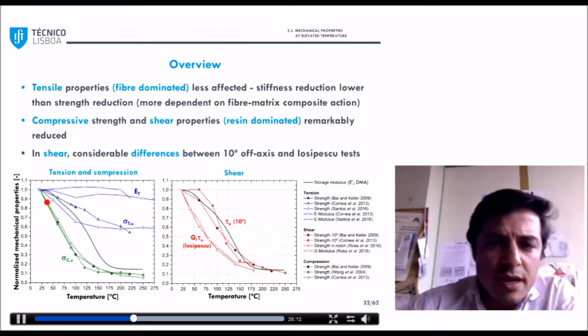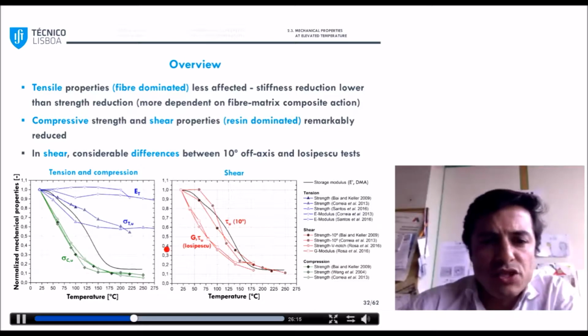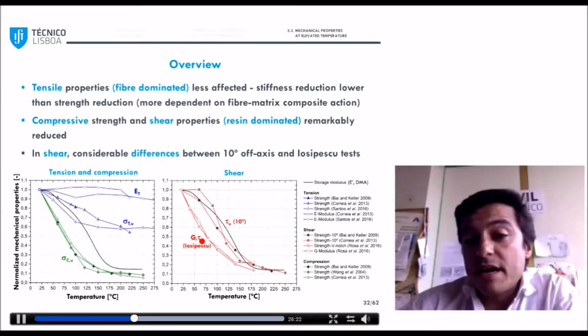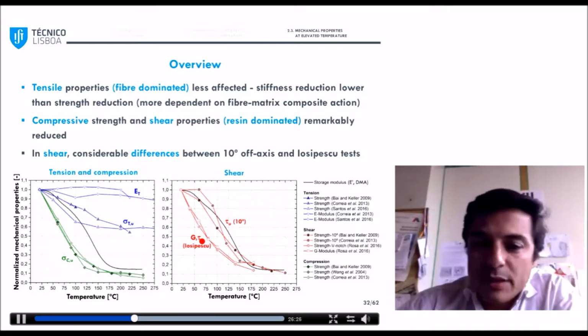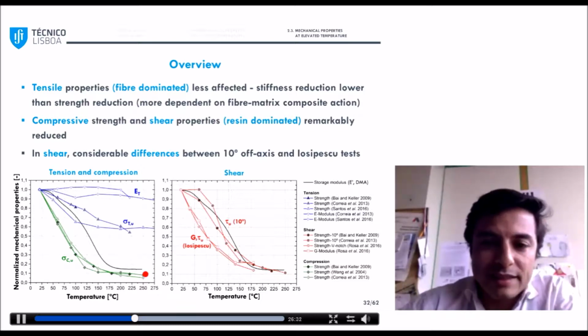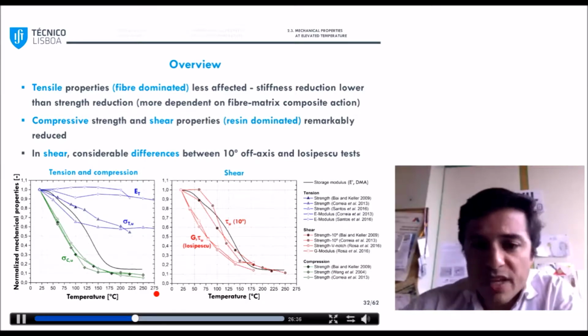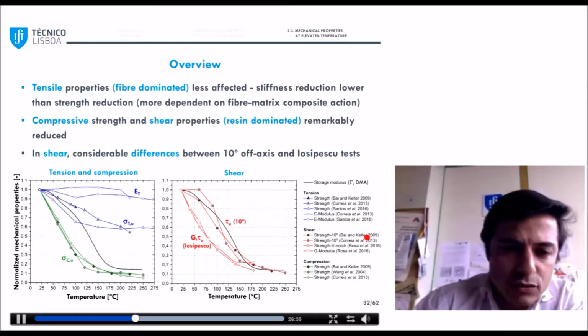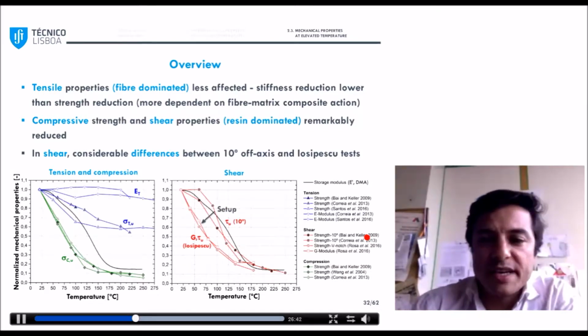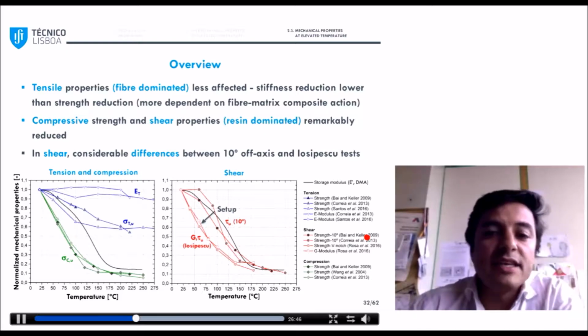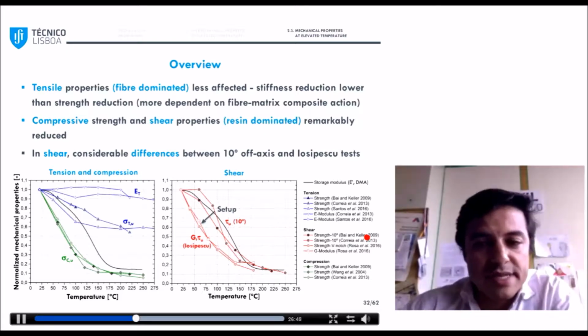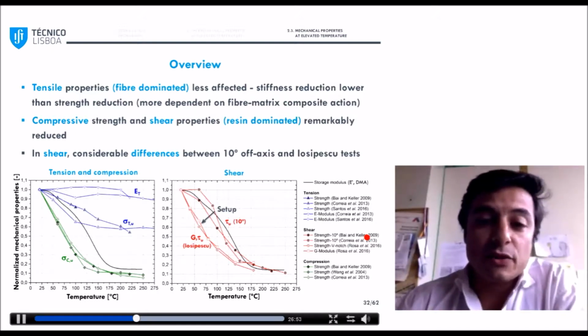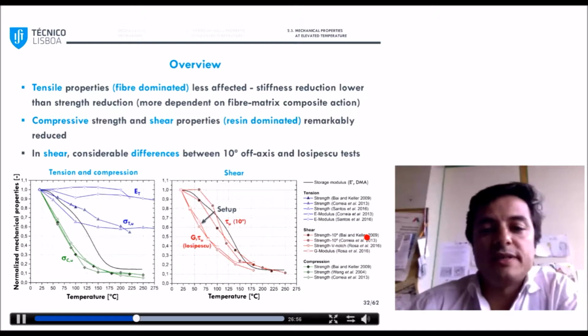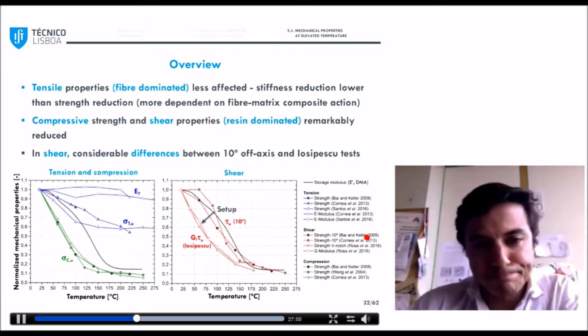Now, compressive strength, which you see in green, and the shear properties that you see here in red, both the shear strength and the shear modulus, are all resin dominated, and you can see that consequently they experience much higher reductions with temperature, becoming almost negligible at the end of the glass transition process. For the shear strength, I would also like to mention the significant differences we obtained from 10 degrees off-axis tests and the Iosipescu setup. So here you see that the setup we use has a big influence because for 10 degrees off-axis tests, we have influence of the tensile stresses in the fibers.